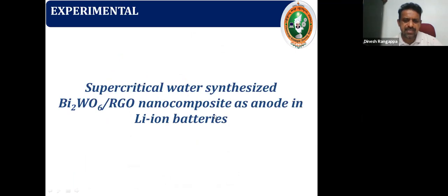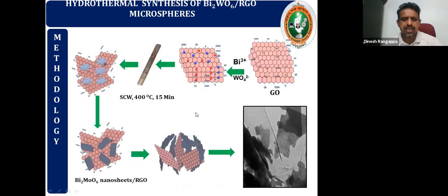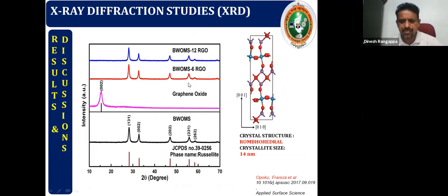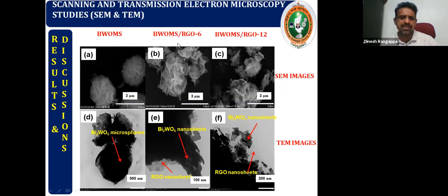Similarly, we prepared bismuth tungstate RGO nanocomposite in a similar reaction, and this is the crystal structure of bismuth tungsten oxide, rhombohedral structure, and the crystallite size is about 14 nanometer. You can see the neat, pure crystal phase of bismuth tungsten oxide and RGO composite. We used 6% and 12% RGO. So sheet-like morphology was obtained, a hierarchical sheet-like morphology confirmed under SEM, and TEM images show the RGO sheet, with bismuth tungstate coated on the RGO sheet.